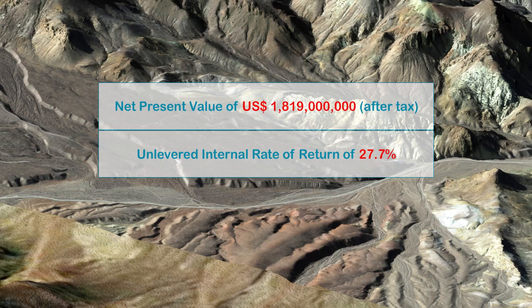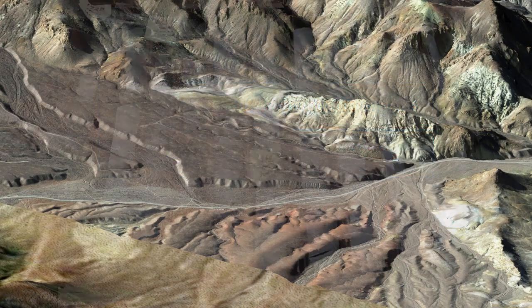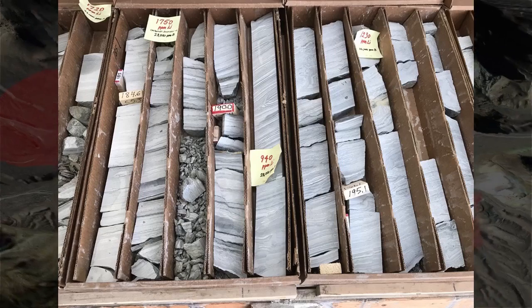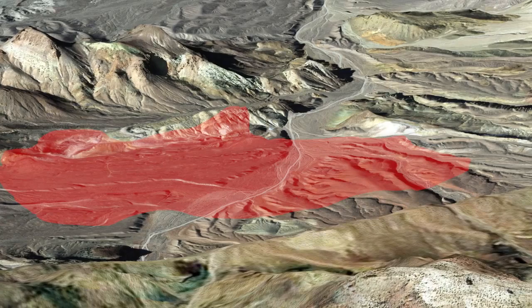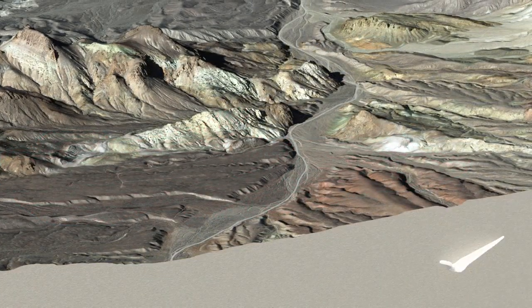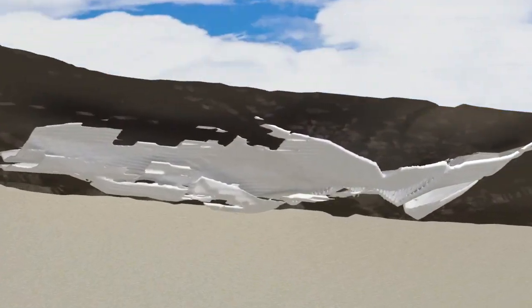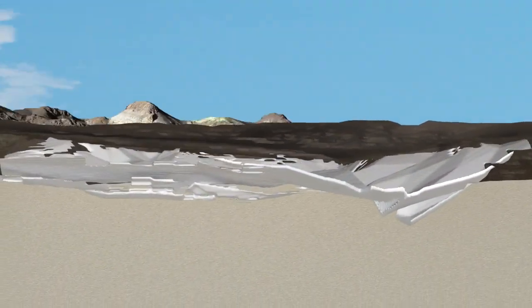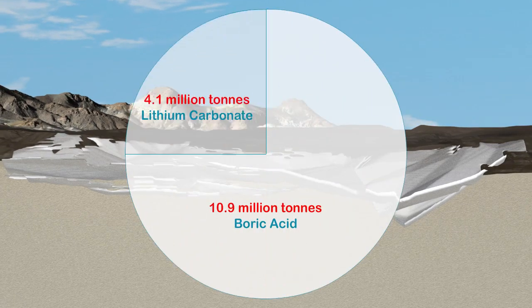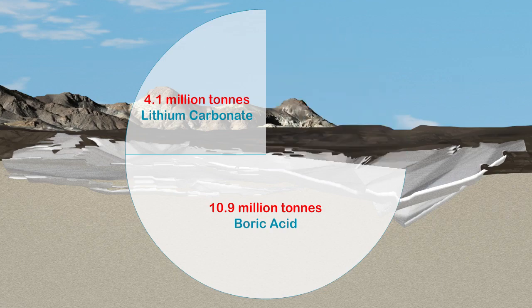Importantly, the preliminary feasibility study demonstrated the potential for Rhyolite Ridge to become a long-life, low-cost, and highly profitable business of global significance. With over 60 drill holes already completed, the deposit is well-defined but still open to further expansion. It occurs as a thick, coherent, and laterally continuous tabular-like body. Based on current drilling, the deposit is estimated to contain the equivalent of 4.1 million tons of lithium carbonate and 10.9 million tons of boric acid.